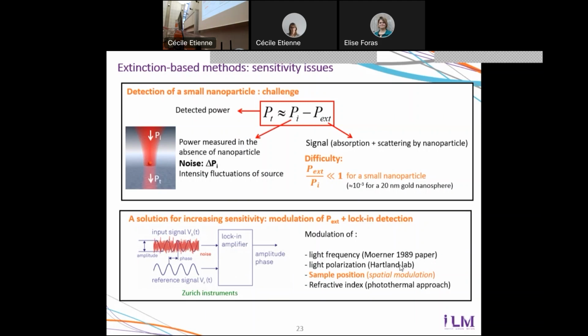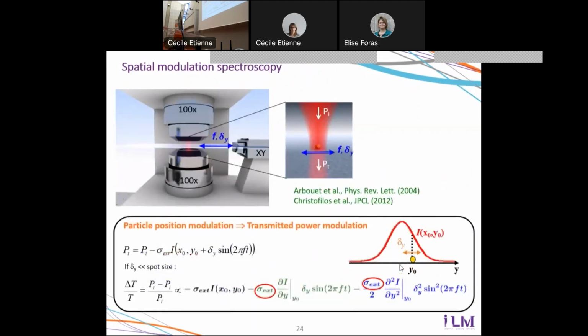So to detect this small attenuation that can be even smaller than the intensity fluctuations of the light beam, one needs a sensitive approach. And the main idea is to make the attenuation oscillate in time and to detect it with a lock-in detection. For this, one has to modulate something in the system to allow this detection approach. What Moerner did in his first paper was to modulate the light frequency. What we do in the lab is to modulate the sample position under the beam. So we move the sample periodically, as shown here.